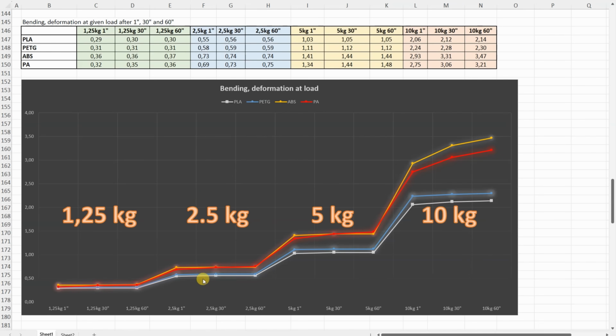For example, the smallest deformation we can see on PLA and PETG. Even under 10 kilograms we can see very minimal additional deformation during that 1 minute. About ABS and nylon, we can see quite a lot of additional deformation during that 1 minute under 10 kilograms. But look at this, ABS under 5 kilograms, almost no additional deformation. This is almost horizontal, unlike with the nylon. This means this is not really the creeping of the ABS, but this 10 kilograms just became too big a load for this material. Unlike with the nylon, which also likes to creep, which you will see soon.